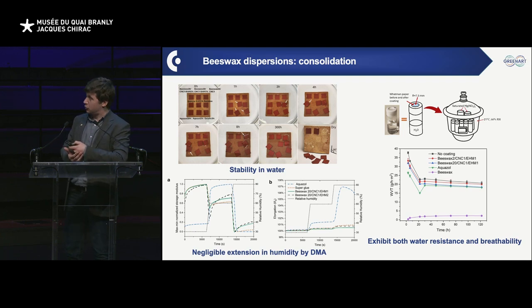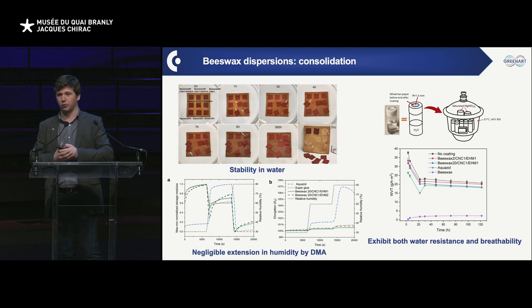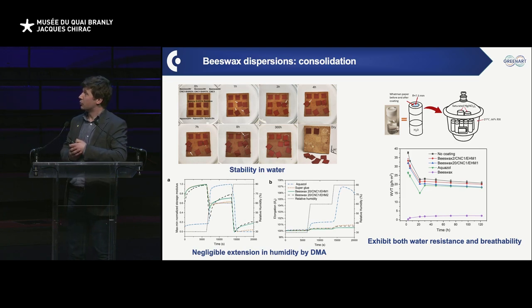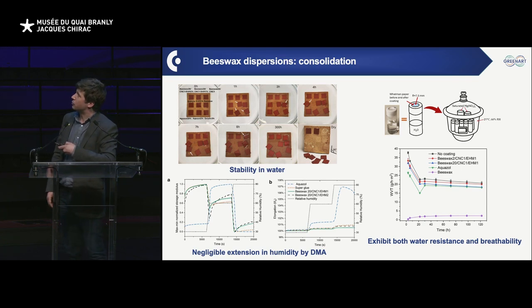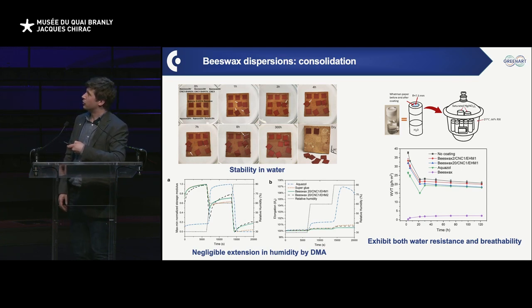And we basically took mock-ups. So these pieces that you can see here that have detached were actually beeswax and red ochre dye or pigment dispersed. We coated or attached it onto a piece of wood, and then we exposed that underwater. Some of them are only pure Aquazol, the one at the bottom. Some of them are cellulose derivative or just the beeswax as well.